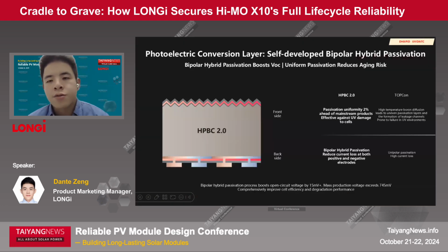And for the HPBC second generation cells, we can largely reduce the UV degradation. We all know that TOPCon experienced very strong, very terrible degradation issues last year. From the technical side, it's coming from the front-side diffusion part, and the aluminum-silver paste doesn't connect well to the wafer, which leads to leakage channels, degradation, and also UVID problems.